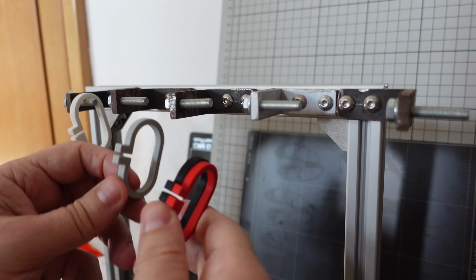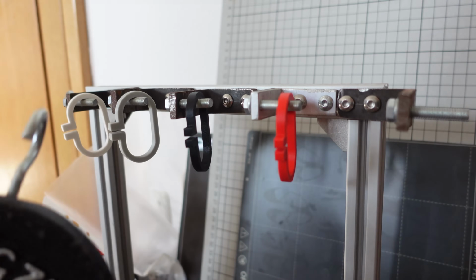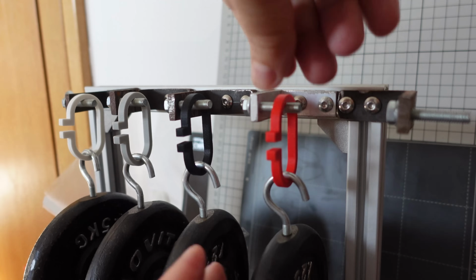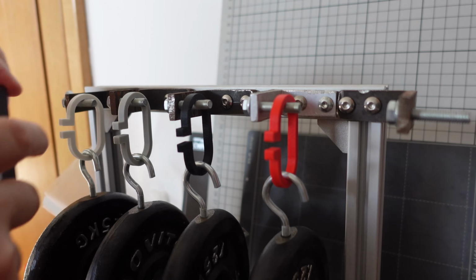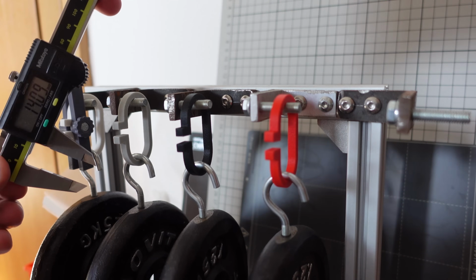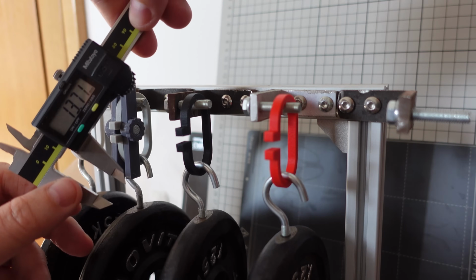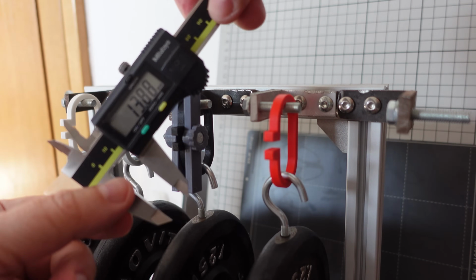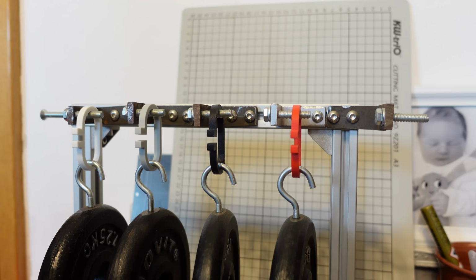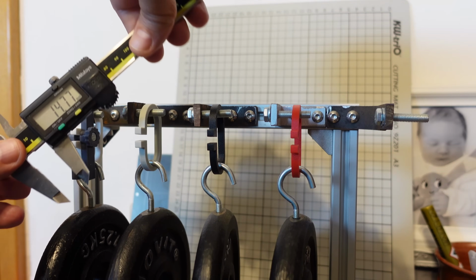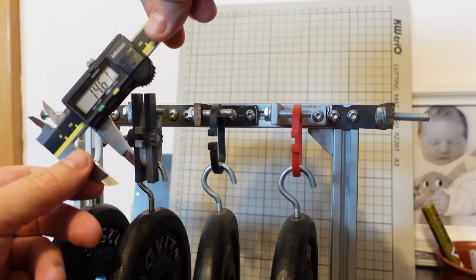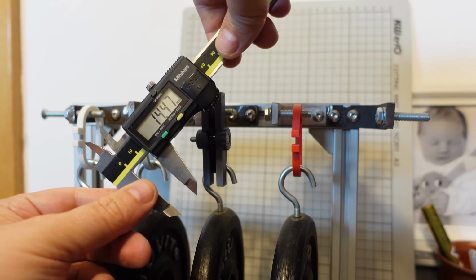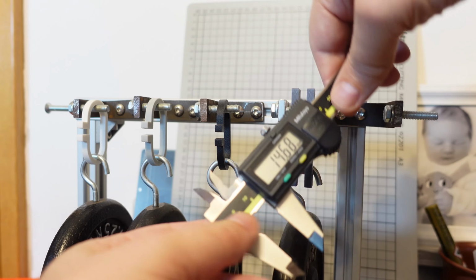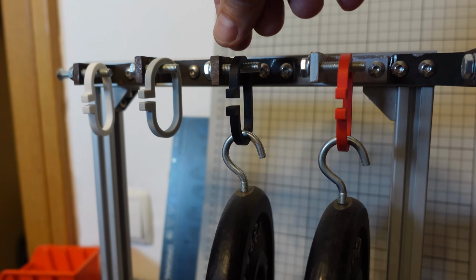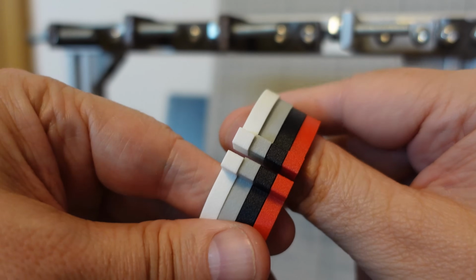The creep test, the deformation under a constant load, which will be 1.25 kg. Visually similar initial deformation on all four objects, let's measure them. 1409. Interesting, 1371. 1388, 1437. I've measured them every day. This is now the fifth one. 1477, 1461, 1447, 1468. And now let's remove the load. And now they look very equal, I cannot see any difference between them.